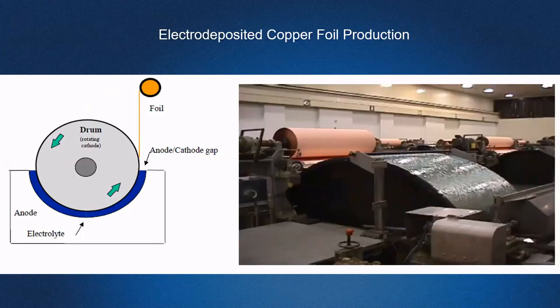So copper foil is made in a couple different ways. The predominant manufacturing technology used for PCB is a large stainless steel drum rotated in a copper bath. I can tell you that if you walk by that plating operation and you have metal in your pocket, you might be in trouble because it's done at very high current. As the drum is rotating, the foil is peeled off, and then that foil is treated in several ways to make PCBs. Some technology is used to make the foil smooth for low loss circuitry, but this foil is used in other systems as well. Battery technology has really advanced in the last couple of years, and it's a big consumer of this type of copper foil.